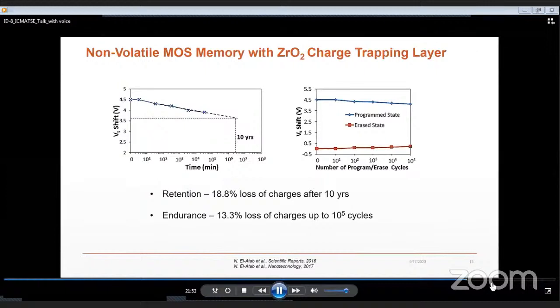Additionally, even though the zirconia islands are polycrystalline, the discrete islands assist in lowering the probability of charge leakage as opposed to a continuous thin film, because only the grain boundaries in the zirconia islands above the defects of the aluminum oxide and tunnel oxide will add to the charge leakage.